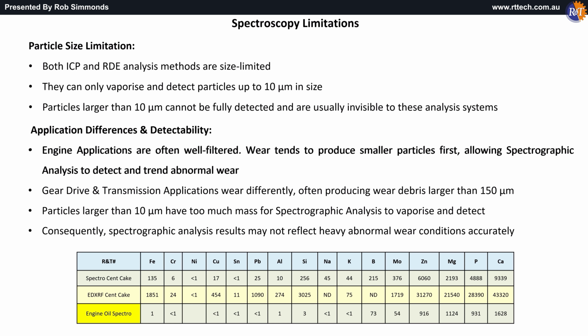Engine applications are often well filtered. Wear trends tend to produce smaller particles first, allowing spectrographic analysis to detect and trend abnormal wear. Gear drive and transmission applications wear differently, often producing wear debris larger than 150 microns. Particles larger than 10 microns have too much mass for spectrographic analysis to vaporize and detect. Consequently, spectrographic analysis results may not fully reflect heavy abnormal wear conditions accurately.